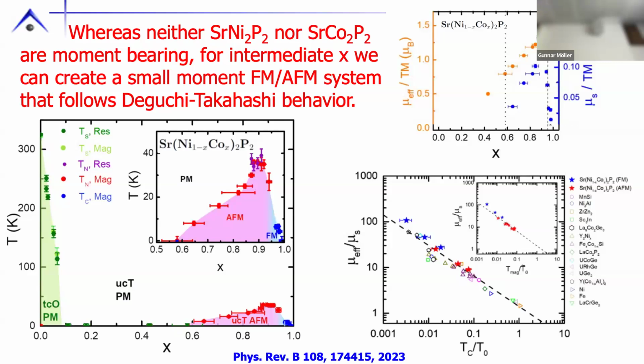So what we're doing now is looking to see if we can find quantum critical points on this side, either with the doping or by applying pressure to some of the ordered ones. And we've already studied the magnetism on this side. So this is a way of generating large numbers of fragile antiferromagnets or ferromagnets. And there are a lot of other members of 122 you can play with. In addition, we're generalizing collapsed tetragonal to other structures as well. Rosa Valenti in Frankfurt and I have been collaborating for over a decade, and we have machinery for actually predicting these in silico now. And unlike many other predictions, these are actually quite accurate because this bond, not bond, is a huge energy scale and it's capturable.